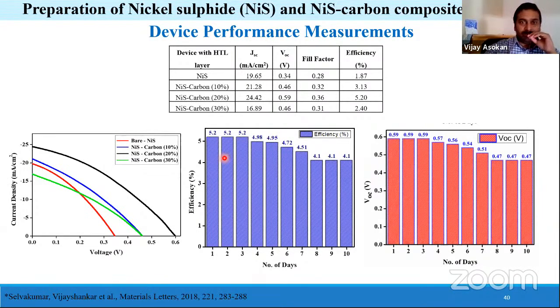At some point, when you keep on increasing the percentage of carbon, it makes a blockage over the whole transport layer. So the possibility for charge carriers to move is getting decreased or reduced, in the sense we can say. So that's the factor we need to consider when we are making such composite. We need to know up to which percentage you can use to get a good efficiency of performance. So that's why we added different carbon percentages and calculated even the degradation point with number of days.